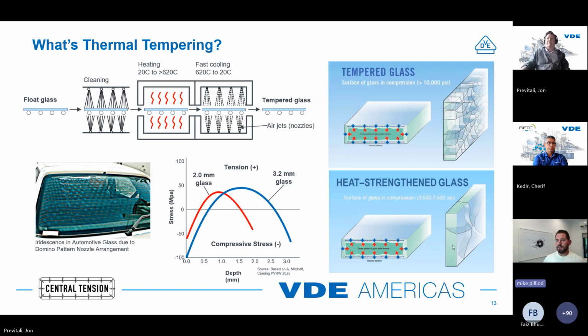Great question. So on the right-hand side, the graphic there is just to illustrate that there's an inner tension area and an outer compression on the surface. They would be different based on the thickness of the glass. As the thickness of the glass changes, you get a deeper depth of layer and potentially more compressive stress on it. But it's fundamentally a function of the glass thickness, the thermal expansion properties, and how the heating and cooling tempering works. So those graphics are just to show that you have an inner central tension and a compressive layer.